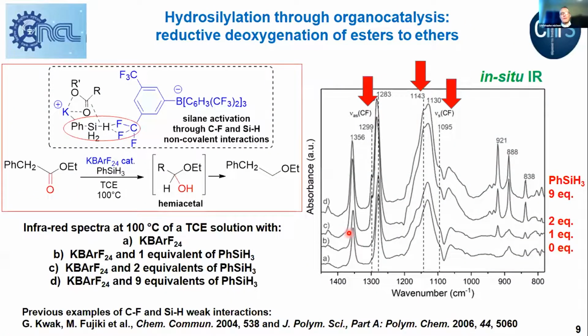In collaboration with Pune, and Kumar Vankar for the calculation part, we developed organocatalysts for hydrosilylation reactions and more specifically reductive deoxygenation of esters to ethers. As shown here, you can see the catalyst we are using. This is a fluorinated borate salt with a potassium cation. And this is the ester that is reduced. We could evidence the silane activation through carbon-fluorine and silicon-hydride non-covalent interactions, the potassium also acting as an activating partner of the ester and the silane.